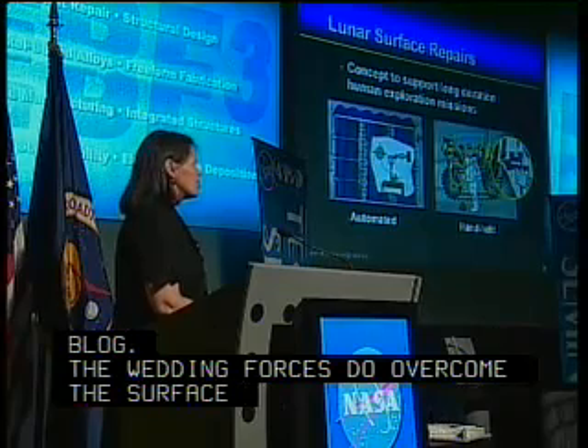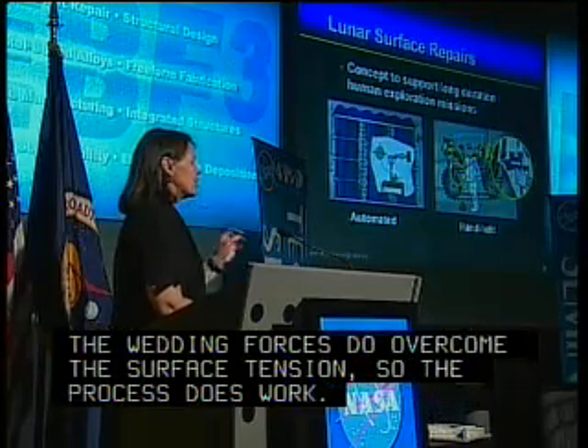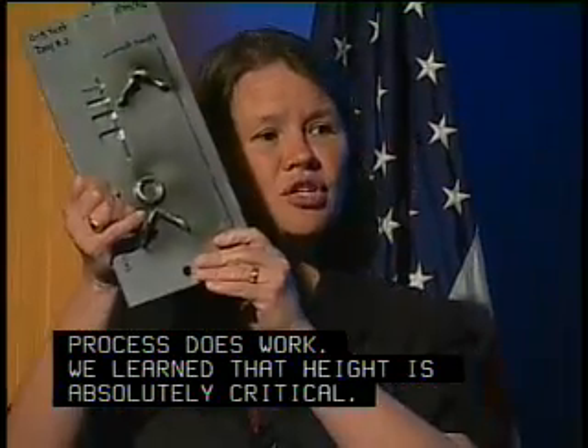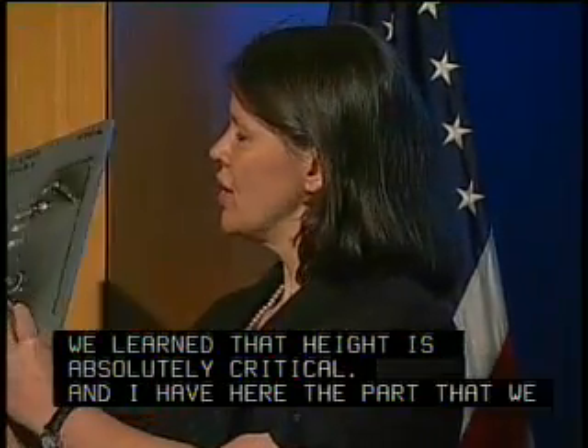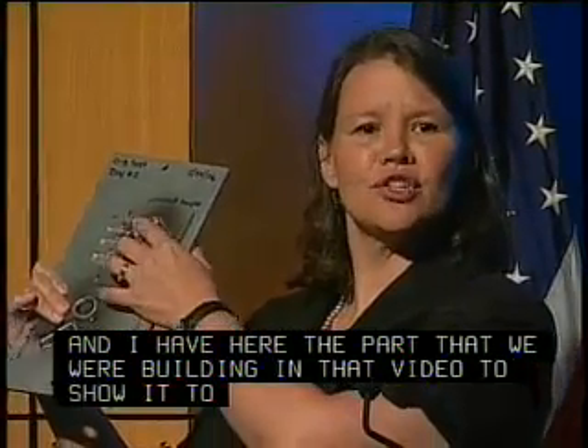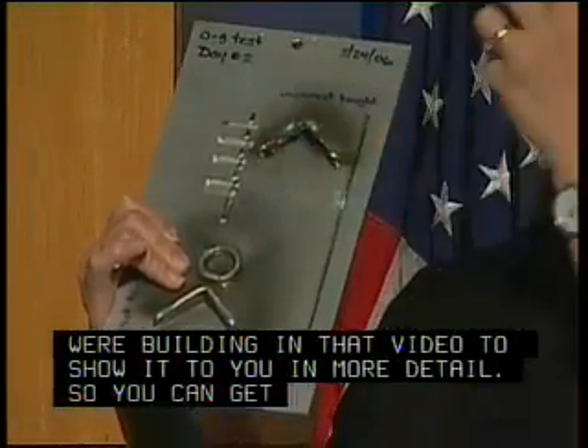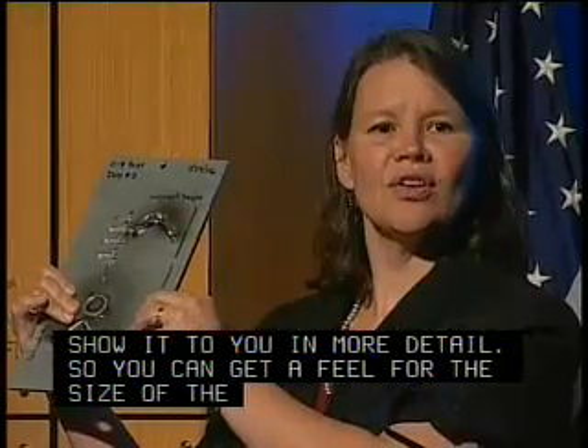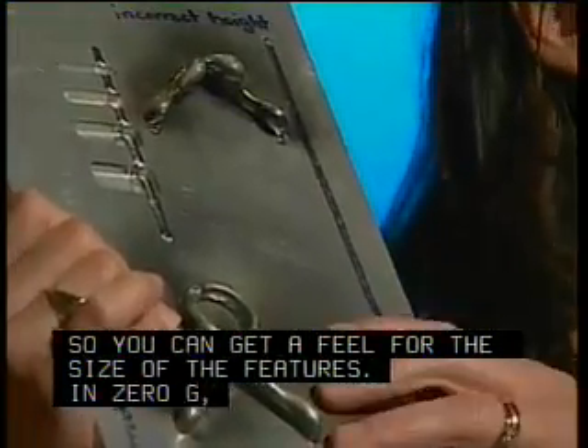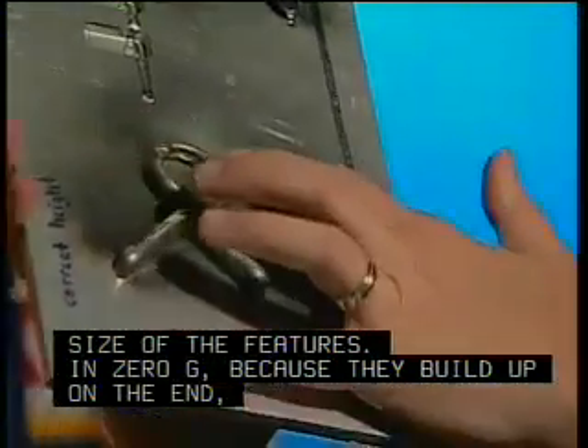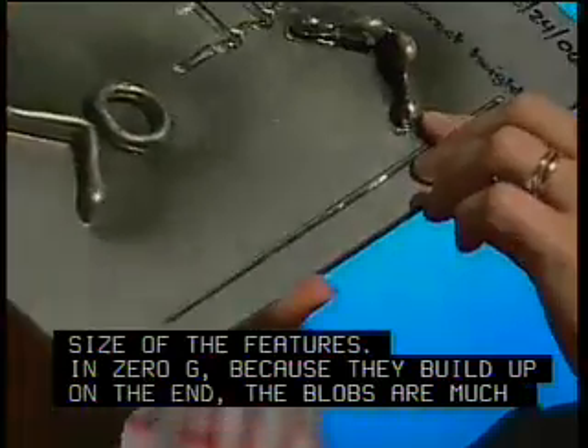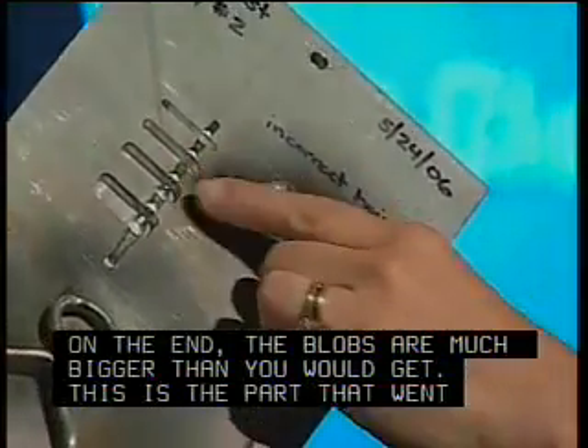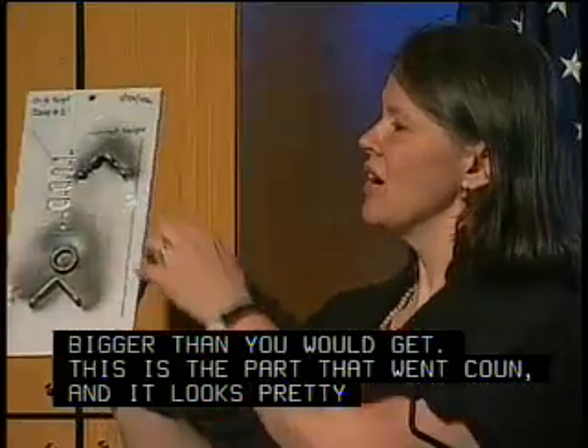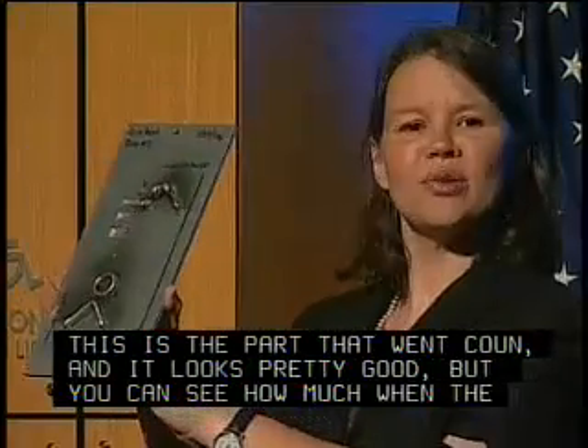The other thing that we've learned is that height is absolutely critical, especially in a reduced gravity environment. And I have here the part that we were building in that video just to show it to you in a little bit more detail so you can get a feel for the size of those features. In 0G, those blobs, because they continue to build up on the end of that nozzle, are much bigger than you would get in a 1G drip. So this is the part that went down, and it looks pretty good, but you can see how much of a surface change we had when the drips started getting away from us.